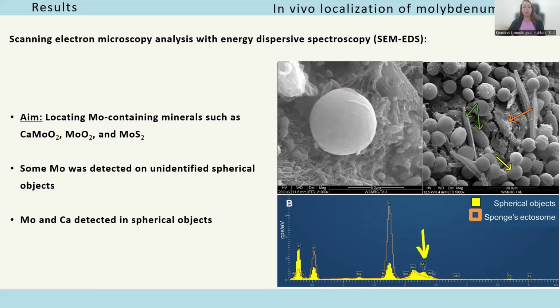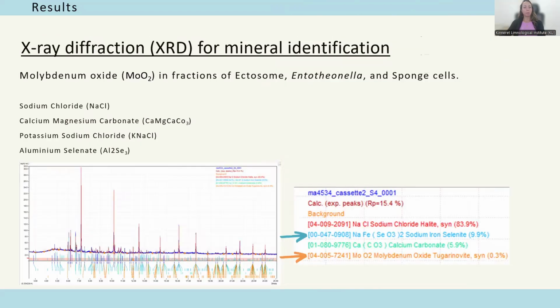In the ectosome, we observed spherical granules, and EDS analysis showed that some of these granules contain molybdenum and calcium. The molybdenum to calcium atomic ratio was close to 1:1, which is consistent with calcium molybdate or powellite crystal. However, I want to be careful here. Based on SEM-EDS alone, we cannot definitively identify the mineral phase. We can say that these are molybdenum and calcium-bearing spherical structures and that calcium molybdate is a plausible interpretation.